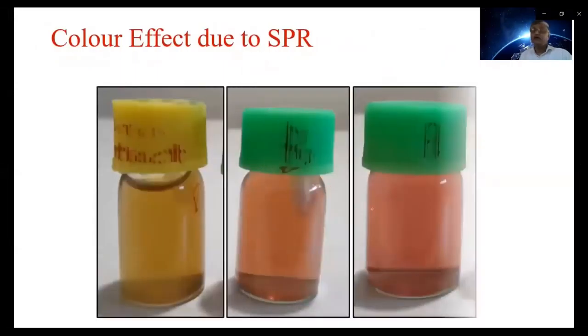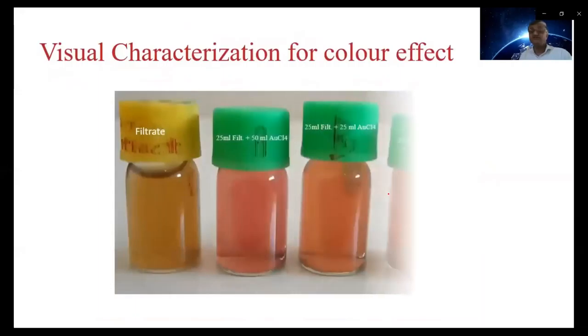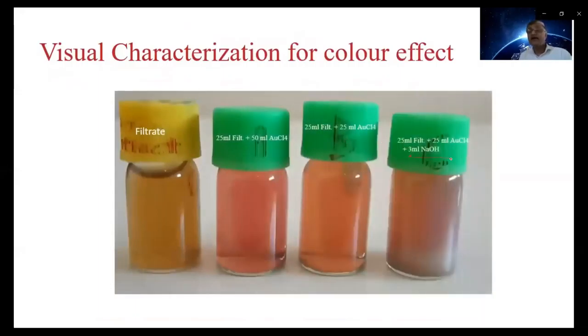Here we can show the effect of various parameters on the color of the formed gold nanoparticles, that is, on the surface plasmon resonance of the gold nanoparticles. Here is the equal proportion, and here we have increased the proportion of gold chloride solution. We have seen the color changes from reddish slightly towards pink, and that indicates an increase in the size. In addition, we have added sodium hydroxide to increase the pH of the solution, and the color changes towards violet, which again indicates an increase in the size of the formed gold nanoparticles.